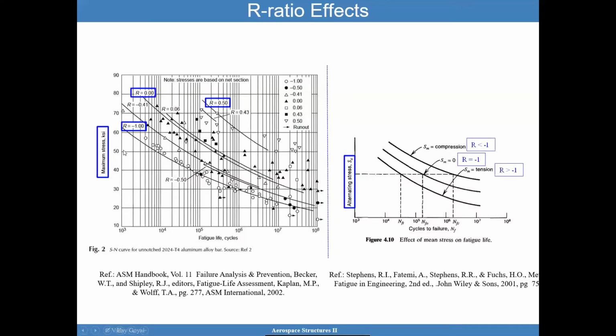So a second situation is a maximum stress of 50, but R of 0. Then I have more number of cycles. Why? Because the max stress is 50, but the minimum stress is 0. So that range is 50. So it's half of what I considered here, right? So here, I have a range that's different from this situation. And that's why I get the higher number of cycles. So again, be careful how you use these plots. Don't pay attention to the labels and try to understand what is going on. What this is telling us is that the greater the alternating stress, the more you get impacted in the number of cycles to failure, but R and the mean stress come into play and are fairly important.